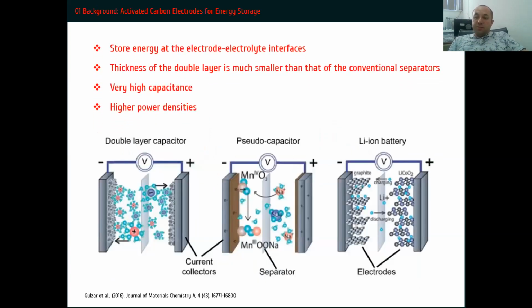Based on the energy storage mechanism, the supercapacitors can be classified into two groups: electrochemical double-layer capacitors and pseudocapacitors. In EDLCs, no electrochemical reaction takes place on the electrode, and the energy is stored only by pure physical accumulation at the electrolyte interface. In the case of pseudocapacitors, the energy is stored directly by fast and reversible redox reactions. The thickness of the double layer is much smaller than that of the conventional separators. They have very high capacitive performance and higher power densities. In EDLCs, carbon-based materials are used as electrode materials, while metal oxides and conducting polymers are used in pseudocapacitors.